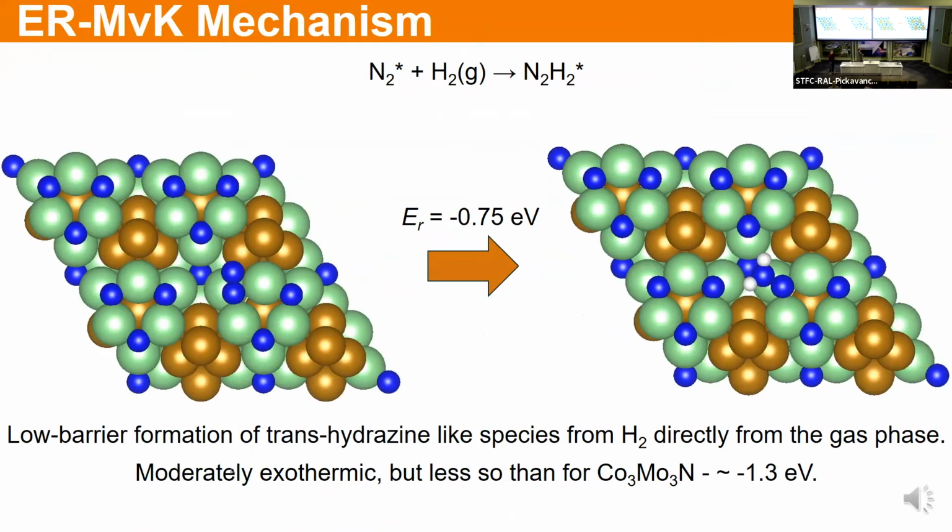Yeah, those are good questions. I'll answer the second because I've forgotten the first question. But indeed, yes, under operating conditions, for the cobalt molybdenum nitride system, the experimental evidence suggests that there is going to be a big reconstruction of the surface because we do have this massive loss of nitrogen. Experimental evidence for the iron molybdenum nitride system suggests that negligible nitrogen is lost from the bulk. So obviously, in a typical sample, most of the nitrogen is going to be way into the bulk. So that's not inconsistent with surface nitrogen vacancy formation.